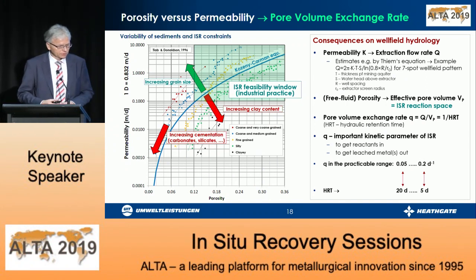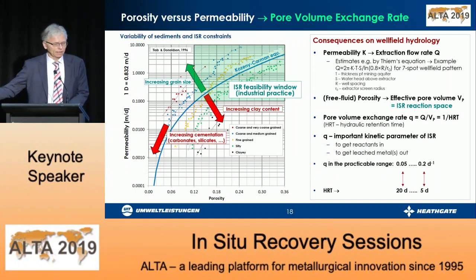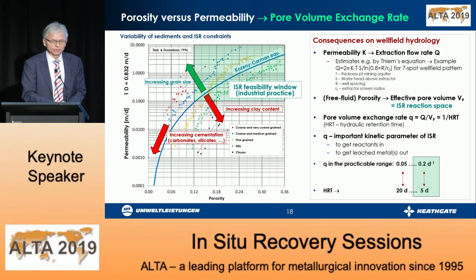Q is an important kinetic parameter to get the reactants in on the one side and to get the leached metals out. The practical range of this Q parameter is between 0.05 to 0.2 per day. We are running the operations more in this highlighted area shown here, resulting in a hydraulic retention time of 5 to 20 days. But in most applications we have, it's closer to 5 days.